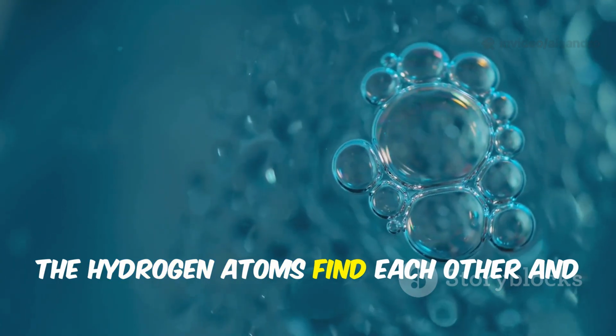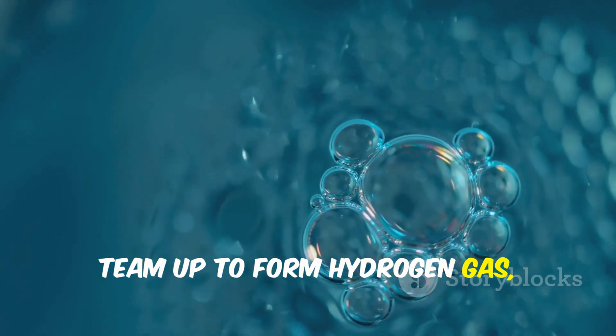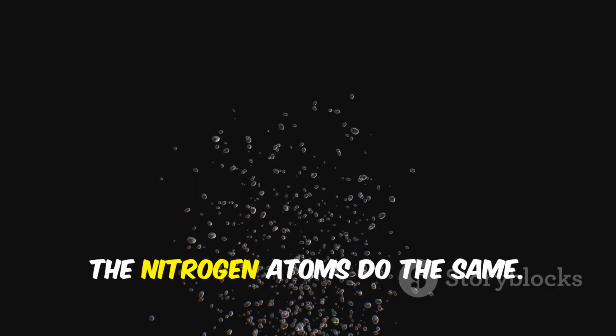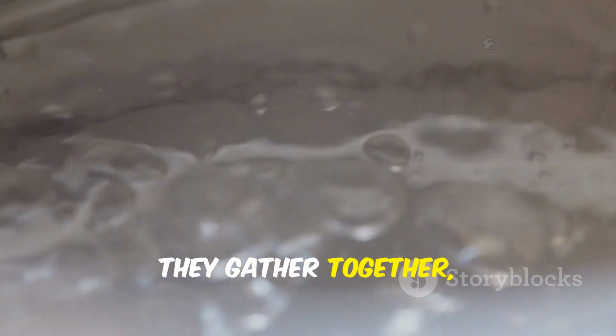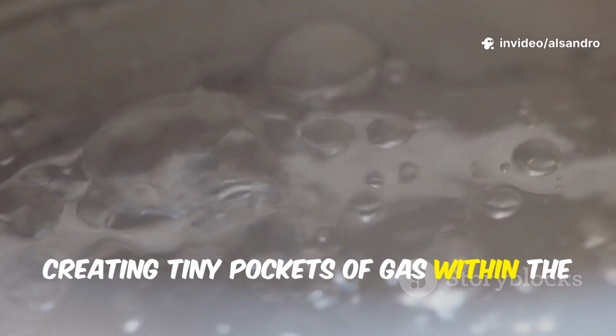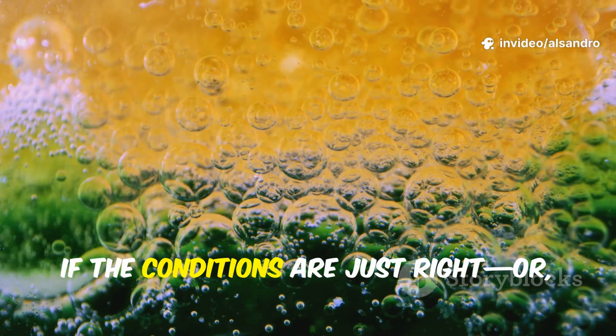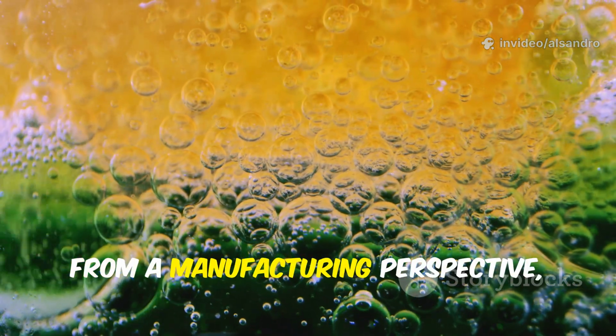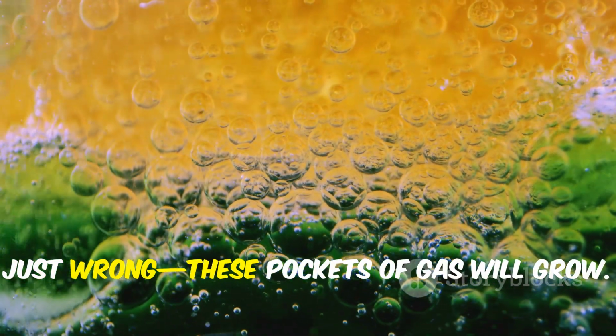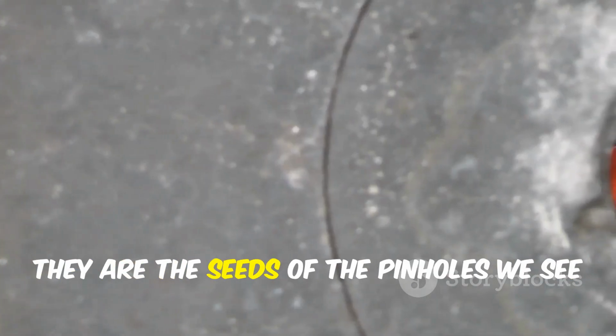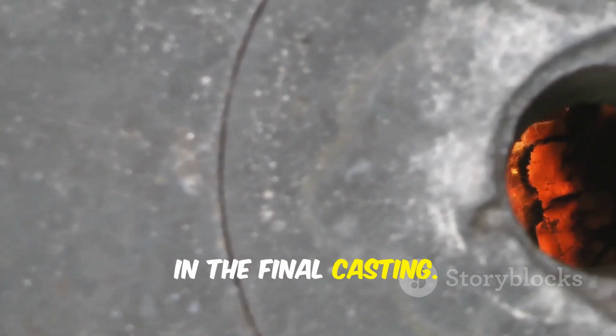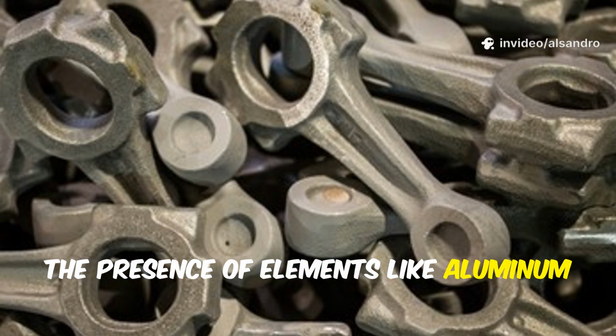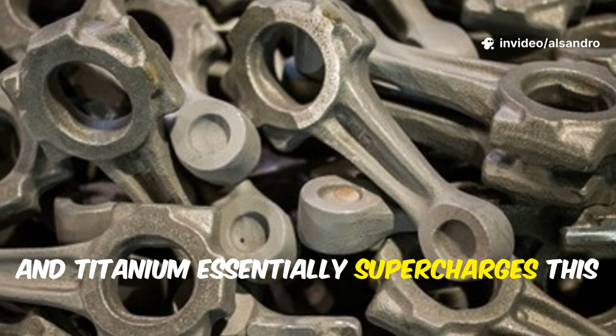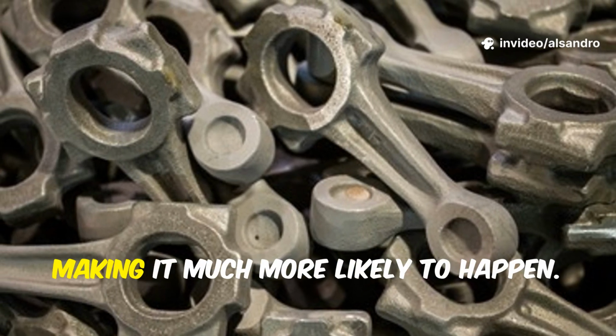The hydrogen atoms find each other and team up to form hydrogen gas, H2. The nitrogen atoms do the same. They gather together, creating tiny pockets of gas within the cooling liquid. If the conditions are just right, or from a manufacturing perspective, just wrong, these pockets of gas will grow. They are the seeds of the pinholes we see in the final casting. The presence of elements like aluminum and titanium essentially supercharges this bubble-forming process, making it much more likely to happen.